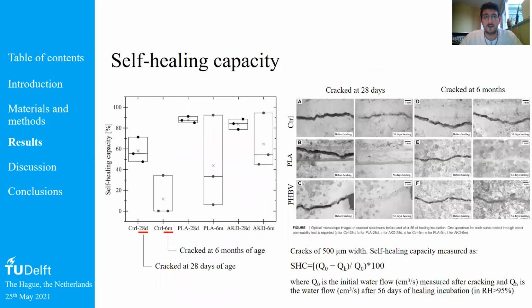Then if we dive a little bit more into the self-healing capacity, what we did was making samples first, and then we cracked them at either 28 days or 6 months, as you can see on the left. We calculated the self-healing capacity of a certain mixture as the ratio between the water flow that was able to pass through the sample just after cracking, and the one that could get through the sample after self-healing. In this case, the self-healing incubation happened for 56 days in a high humidity chamber at a relative humidity higher than 95%.